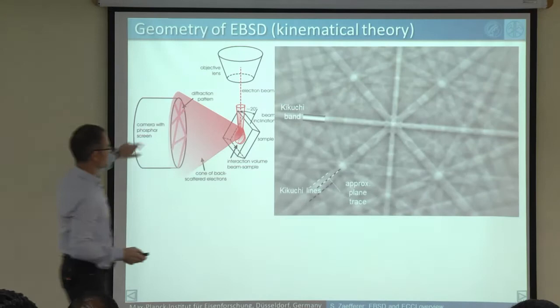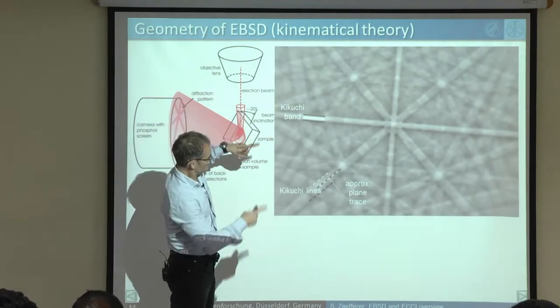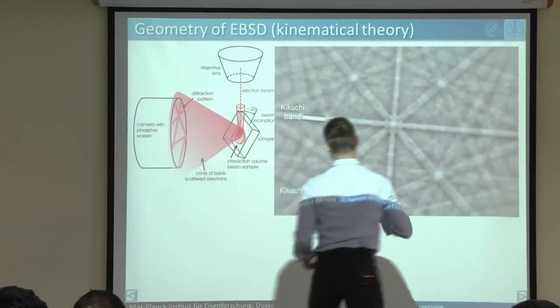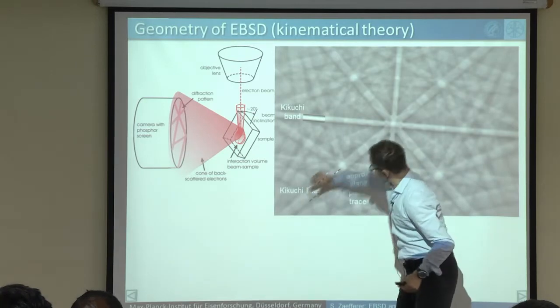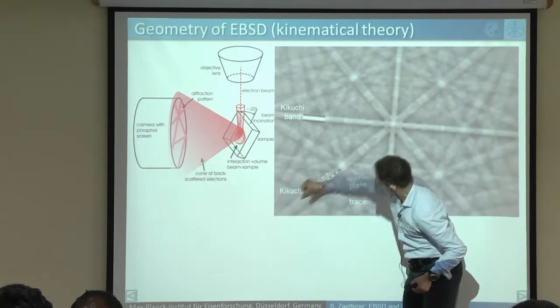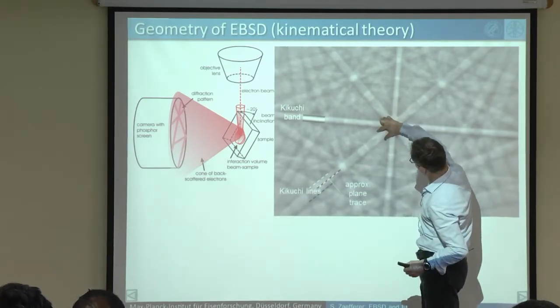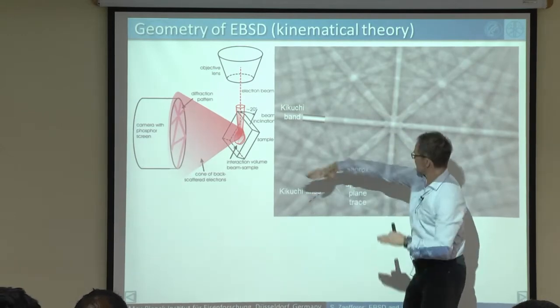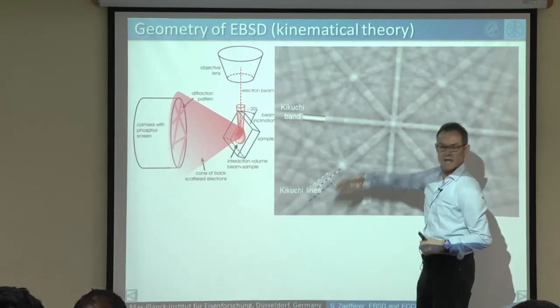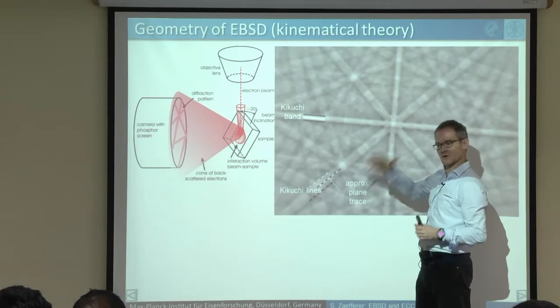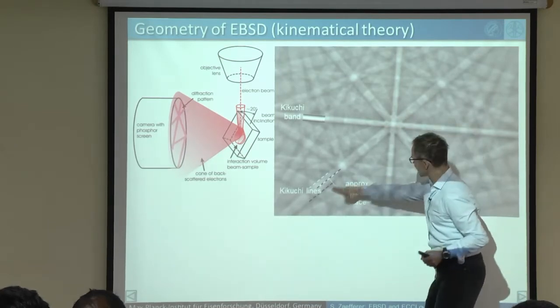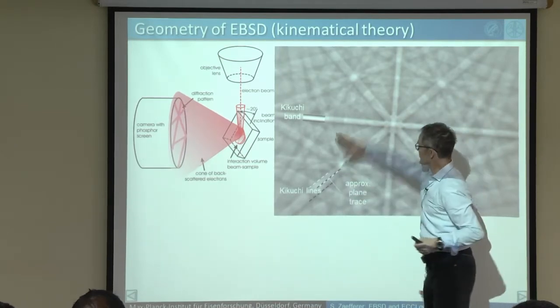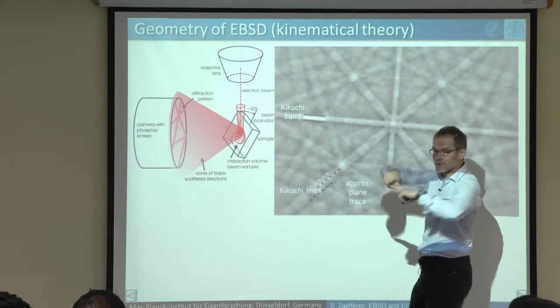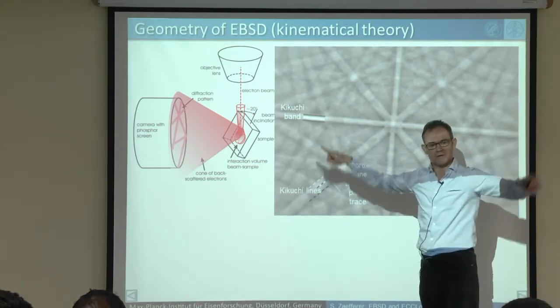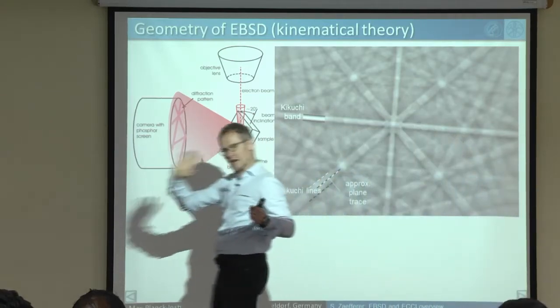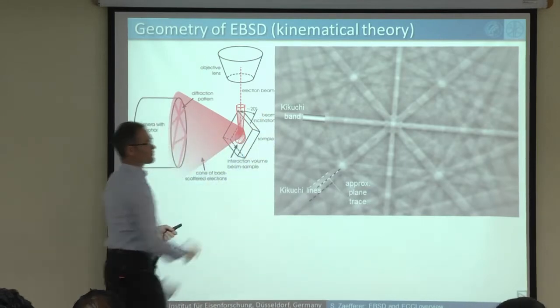And if you look back here into these pictures here, you actually see that it is not perfectly straight lines. For example, this band here, it's a bit wider here than it is here. So you see, it's actually slightly curved. It's a hyperbolic cut through, it's a conical cut and making actually a hyperbola with respect to the screen. All of these lines have a slight hyperbolic shape. But for the time being, we can assume that it's almost perfectly straight.